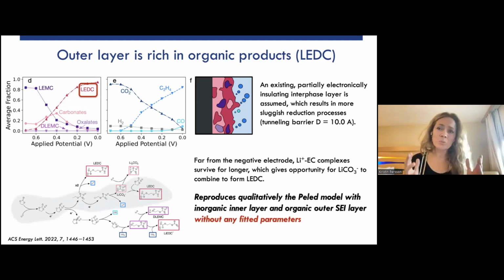And this very simple, but yet informed by this large reaction network, KMC simulation reproduces qualitatively the Peled model with a predominantly inorganic layer that then gets covered via a more organic majority layer. And this has, again, no fit parameters.